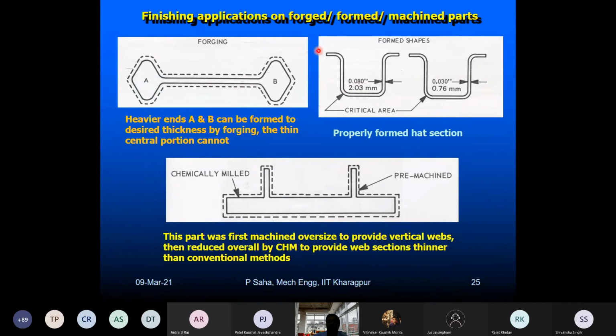Or, for example, this is an example of forming. When you form by a process, maybe extrusion or some other process, these are some of the critical areas where wrinkles may come, and it may even fail. So how do we avoid this? The thinner it becomes, the more critical it is. So in forming we cannot go to such a small thickness. We restrict it, stopping at roughly 2.03 millimeter. But my final dimensions will be achieved through chemical machining, and this 2 millimeter will be brought down to 0.76 millimeter, so roughly 0.6 millimeter will be machined on both sides, and we get these dimensions.